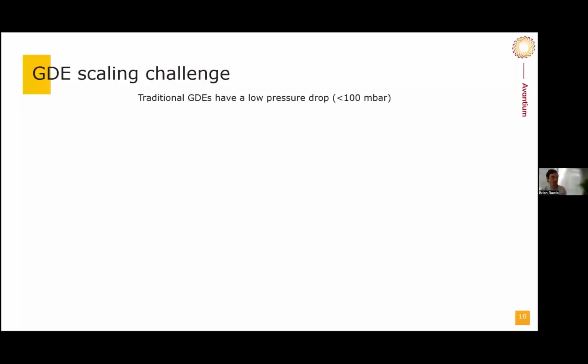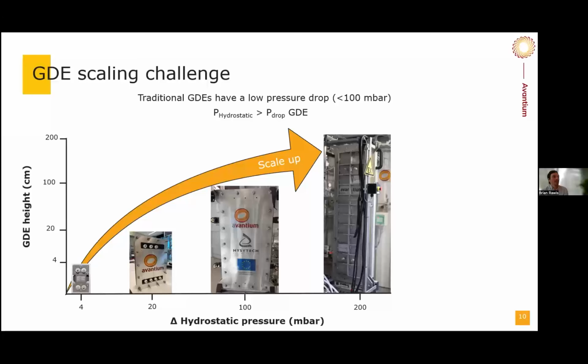However, with GDEs, it becomes quite tricky to scale these electrodes, because they have this low pressure drop, they're very porous. If you work with a liquid electrolyte, you often have a problem when you scale up your cell that the hydrostatic pressure, so the liquid pressure that is exerted on the electrode, is often greater than the pressure drop of the GDE itself. So you can see as we scaled from our 10 square centimeter cell all the way up to our 0.2 square meter cell, we noticed some interesting things happening with the flow properties of our GDE.